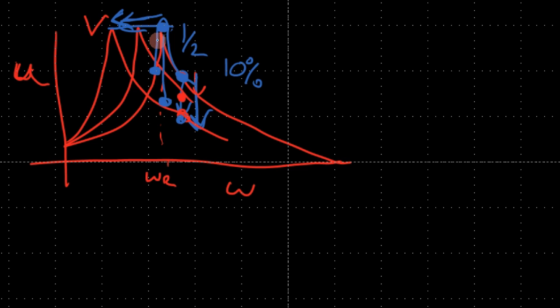This is a common technique employed. Just showing a basic electrical diagram where we have 90 degrees phase up here and negative 90 here. Below the resonance frequency we have a capacitor type behavior, and between resonance and anti-resonance many times we have inductive behavior. Above the anti-resonance frequency we again have capacitive behavior. You don't want to drive your transducer above the resonance frequency too high because at that point the material cannot respond.